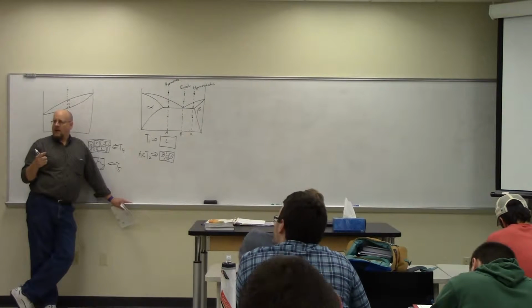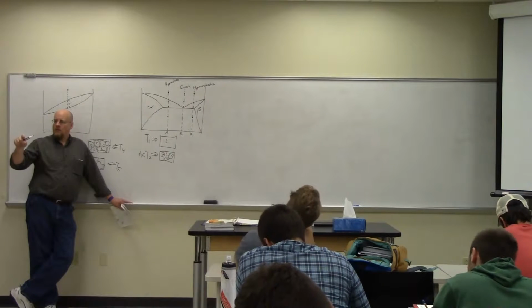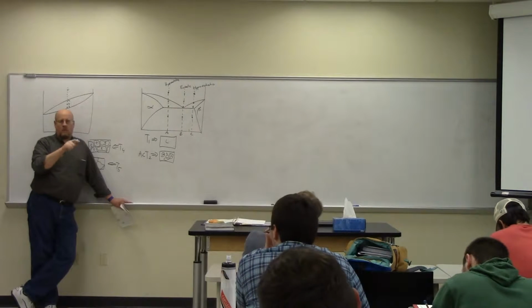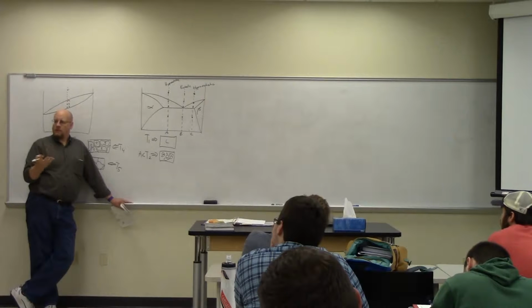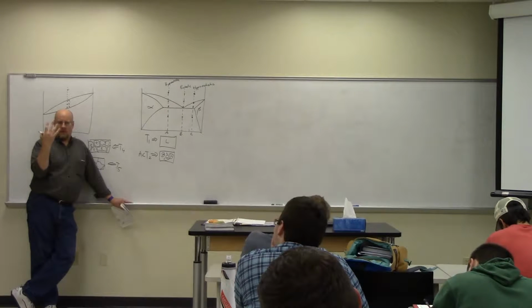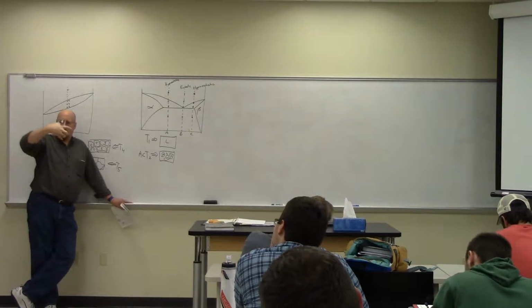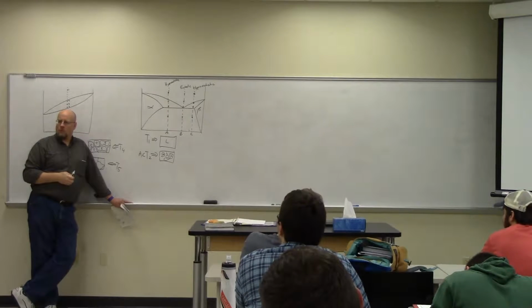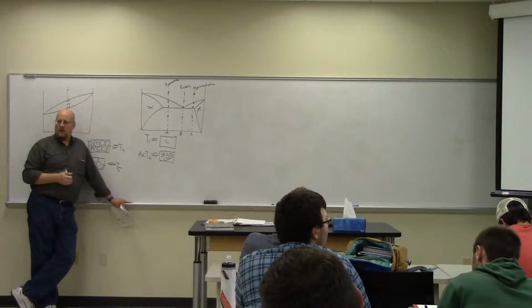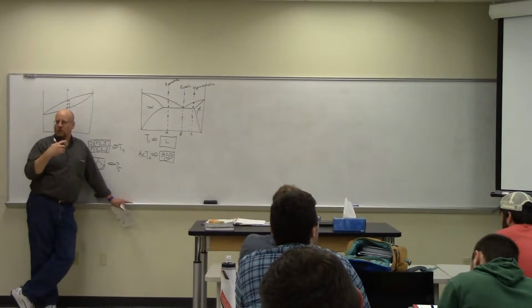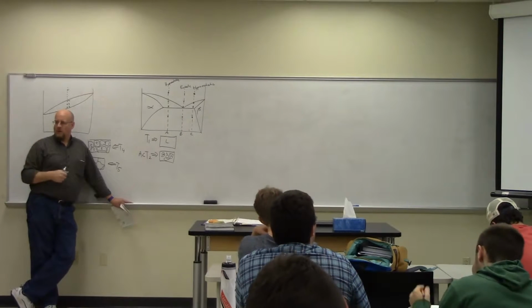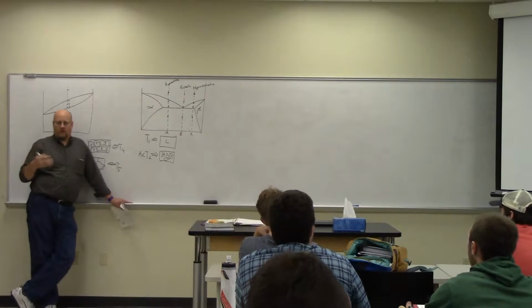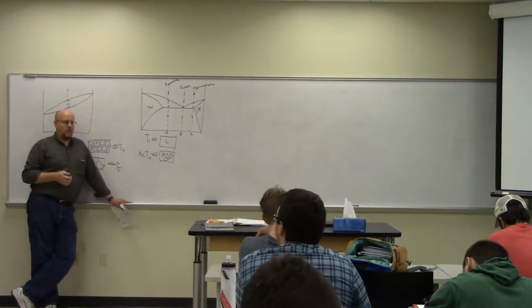You can also do that by drawing a line and counting how many grain boundaries I cross in a given line, so many grains per line means so many millimeters per grain, and then I can do the cross-sectional analysis that way. So you can do it one-dimensionally, two-dimensionally, or three-dimensionally. And typically you do it two, because that's what you analyze microscopically.